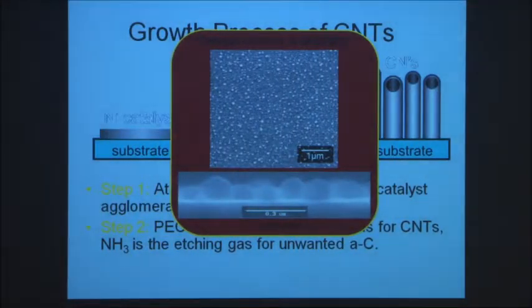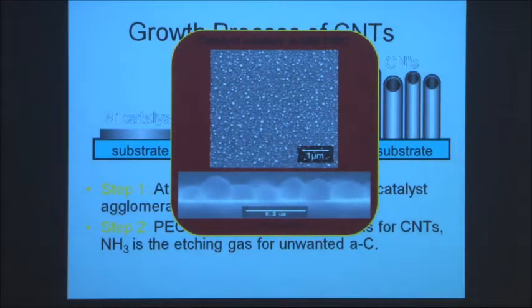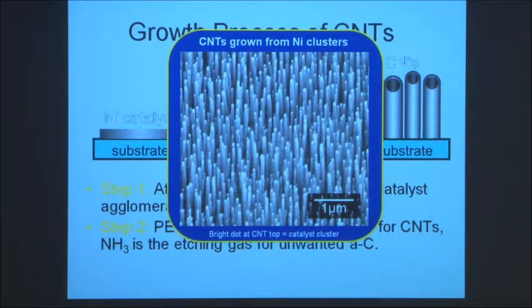Here's an example of the nickel after it's been heated. You can see you get these little balls produced, and the balls vary a little bit in size because you're not controlling what size these nickel thin films will actually end up being. So you get quite a distribution of these nickel dots. But the nickel dots then lead to the growth of the carbon nanotubes, as shown here.